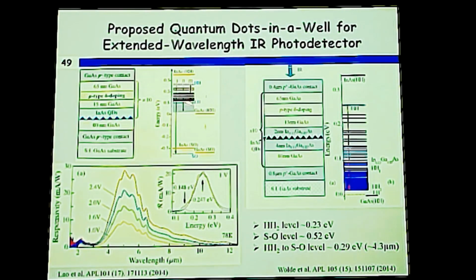However, to make this state a bound state, we can use aluminum arsenide, with a high energy gap, instead of gallium arsenide. So the barrier edge will go there. This SO band will be a bound state. Whenever there is a high energy barrier, the dark current will become much smaller because of the high energy barrier. So the operating temperature can be expected to go much higher than this temperature.